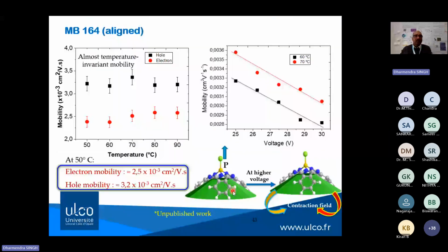Later on, we aligned these materials. When the material is partially aligned or well aligned, you will get better mobility. For example, here due to the higher alignment, the mobility was on the order of 10 to the power minus 3, and this material showed ambipolar mobility.